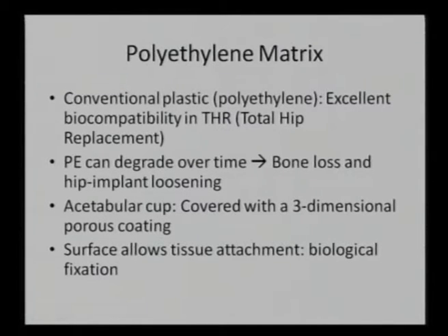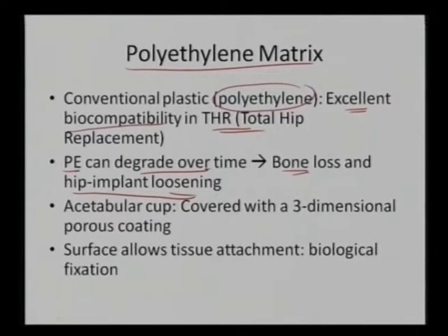So we know that for the polyethylene matrix, conventionally polyethylene has shown to be excellent or exceptional in terms of biocompatibility, such as in total hip replacements. In THR surgeries, polyethylene has been shown to be a very excellent biocompatible material. But the problem with this is that polyethylene can degrade over time. That might create some bone loss or hip implant loosening, because once we are losing some material, it always creates some gaps or spaces between the implant and the bone. So for that, we want the polyethylene coating to survive for a very long time.